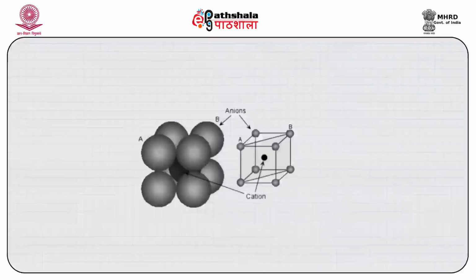It states that a coordination polyhedron of anions is formed about each cation in such a way that the cation-anion distance is determined by the radius sum and the coordination number of the cation by the radius ratio, and we will illustrate this soon. The simple case which we discussed earlier refers to 12 spheres touching the central sphere.